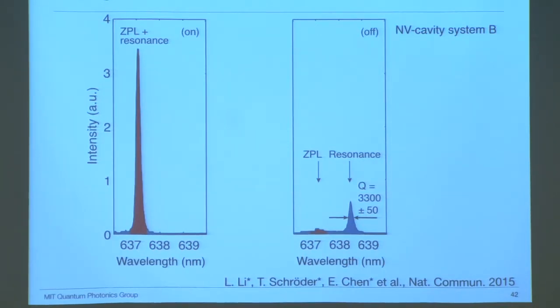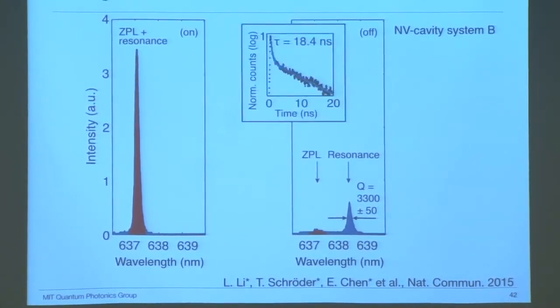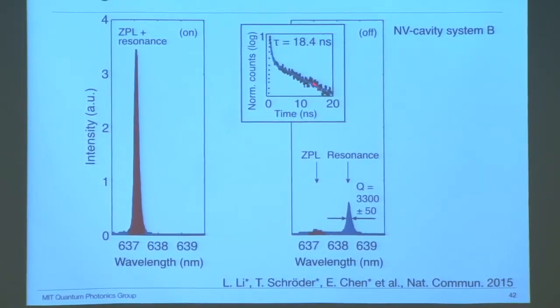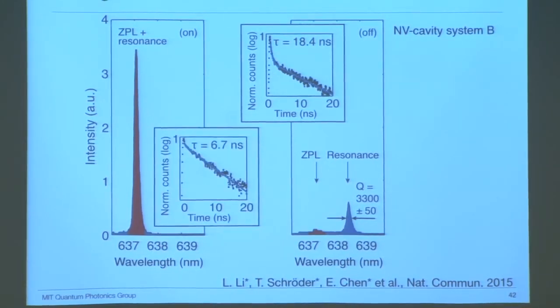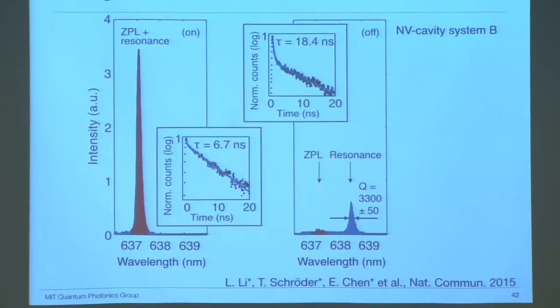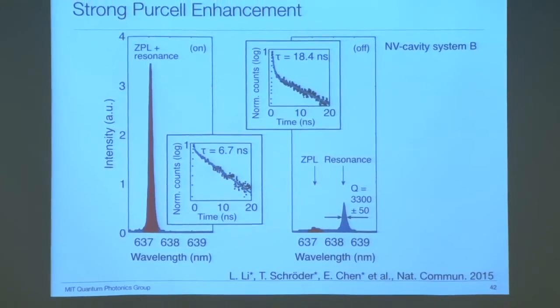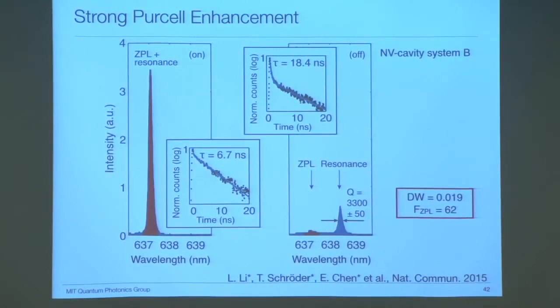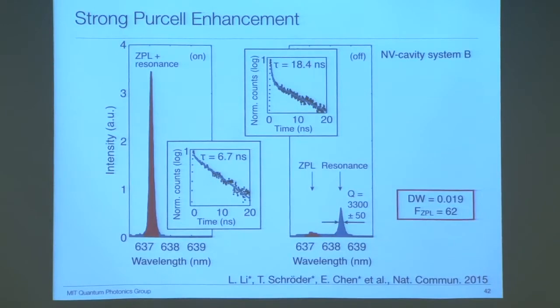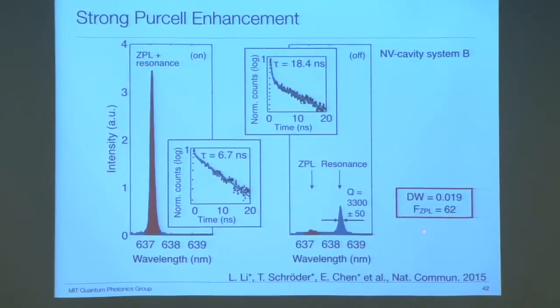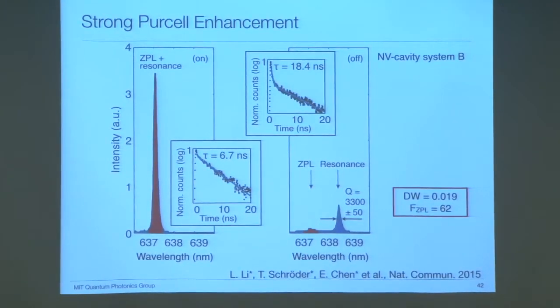And we also check the lifetime of the NV center. For the off resonance case, it's about 18 nanoseconds. When the NV ZPL is on resonance, the lifetime decreased to 6.7 nanoseconds. And by using both intensity and lifetime data, we are able to deduce the original Debye-Waller factor for this ZPL, and also the Purcell factor for the rate enhancement.